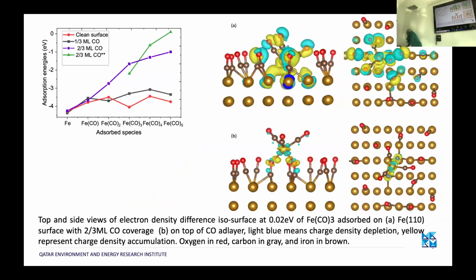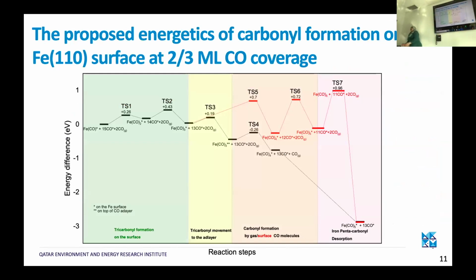So at the end, everything was also supported by analysis of the charge density differences to explain what was going on. And at the end, you do all this hard work to get this kind of diagram. These are the 2 possible pathways that we have identified. But this is very relevant. So you have different transition states, intermediates, and so on, until at the end you end up with this pentacarbonyl desorption that requires the involvement of other CO molecules in the system.